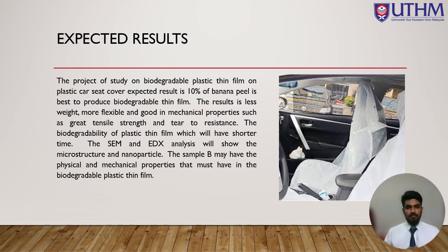So, in this process, the result we expect is that 10% banana peel is best to produce biodegradable thin film because the result will be less weight, more flexible and good in mechanical properties such as great tensile strength and tear resistance. The biodegradable plastic thin film will have a shorter time to biodegrade. The SEM and EDX analysis will show the microstructure and the nanoparticles of the samples A to E. Sample B may have the physical and mechanical properties that a biodegradable plastic thin film must have.